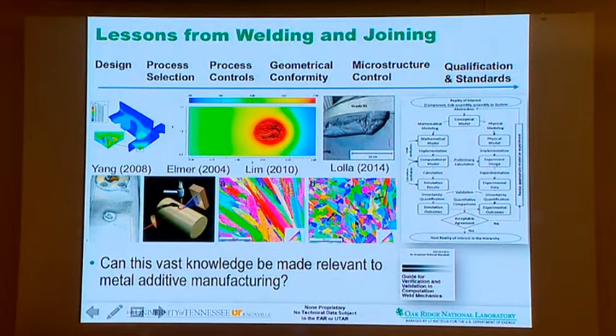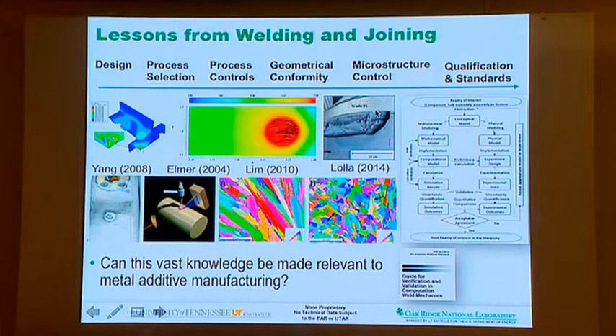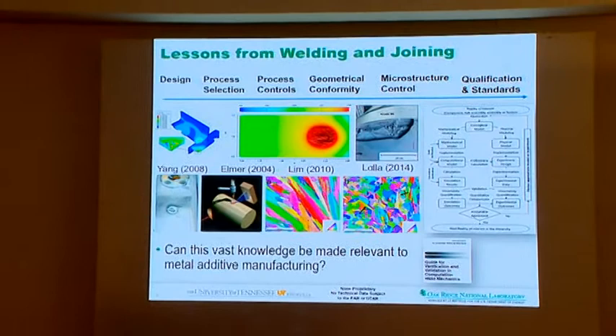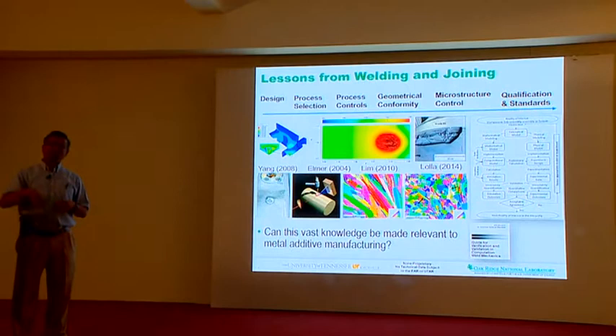In addition to that, once you welded it, you put it in a service, and they degrade most of the time, because we are always in a metastable condition, when you put it in a high temperature service, slowly but steadily the material system is moving towards equilibrium. We can call that a material degradation or moving towards equilibrium. So in that case, we have a stellite cladding on top of steel, and then one of them failed because of alternating loads in a gas turbine engine. So we understand that too. And if you have all that information, we can actually put it together as a computational tool, and we do have a verification and validation for computational weld mechanics.